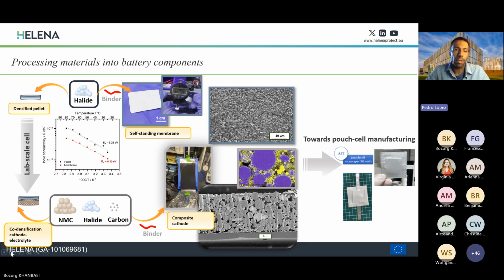As well, on the composite cathode, we've been working on the formulation of the composite laminates, which include the high nickel content NMC with the halide electrolyte and the carbon. And as you can see here, we have developed composite cathodes with a high loading up to 4 milliampere hour per square centimeter to ensure, again, high energy density application. And here we're also looking for improved particle contact between the materials contained within the cathode laminate.